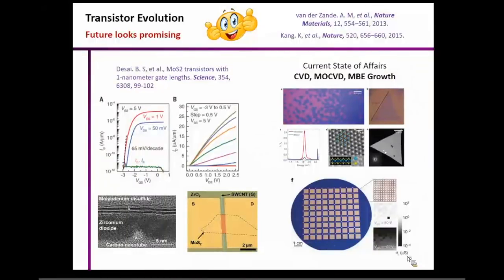Right? And the challenge that still exists is that how do you integrate this synthesis on silicon platform, on that back end of the line processing, which requires lower temperature, because we know that the 2D materials can be grown on many other substrates at higher temperature with very good quality and very good yield and with high mobility numbers. But on silicon, the challenge is whether you can bring down this processing temperature. So that challenge still exists. But looking at what has happened just within like 5 years of this materials becoming in the research field, it's actually very promising.